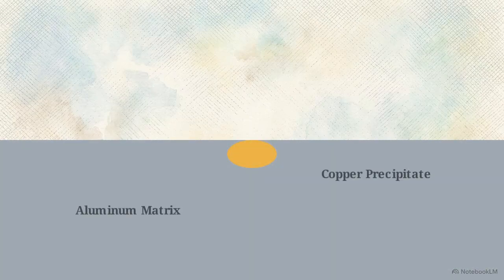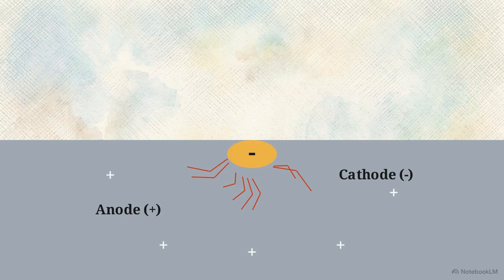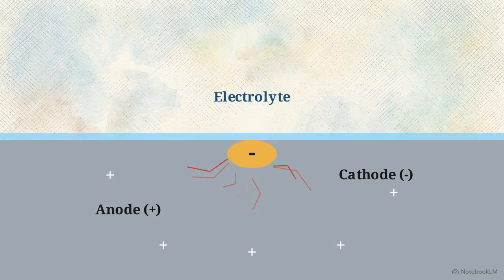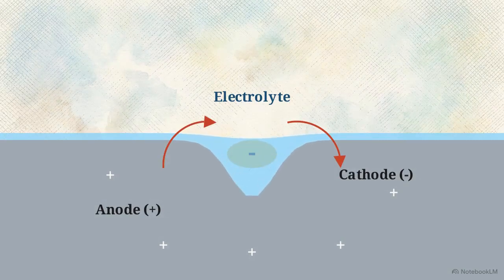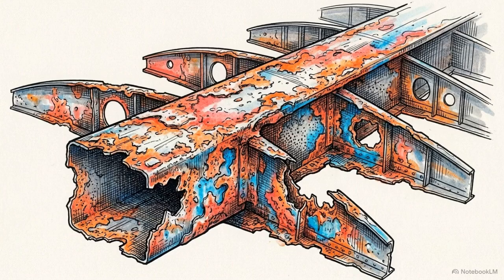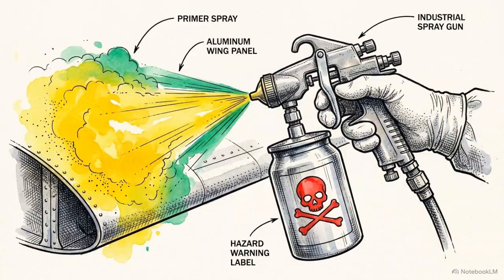This creates an electrochemical contradiction. Within the alloy, these copper precipitates act as localized cathodes relative to the surrounding aluminum matrix. When moisture or marine chlorides introduce an electrolyte, it completes a microgalvanic cell. The aluminum matrix is eaten away through pitting corrosion. The alloying elements that provide structural strength are the same elements that create a specific electrochemical vulnerability when exposed to atmospheric conditions. For 80 years, the industry suppressed this microgalvanic destruction with chromate conversion coatings, treatments based on hexavalent chromium.